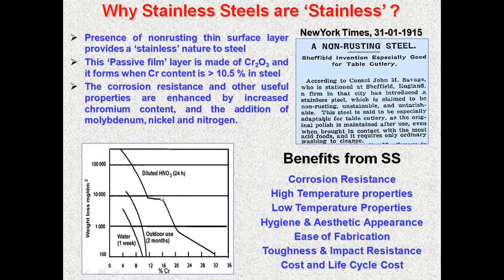But if you go to a corrosive environment, as much as you increase, the corrosion rate is coming down and down. People can add, today commercially, up to maybe 30% chromium in stainless steel, forming the superaustenitic stainless steels. What are the benefits from stainless steels? Corrosion resistance, high temperature properties, low temperature properties, hygiene and aesthetic appearance, ease of fabrication, toughness and impact resistance, and cost and life cycle cost. These are some of the best benefits that one can get from stainless steels.